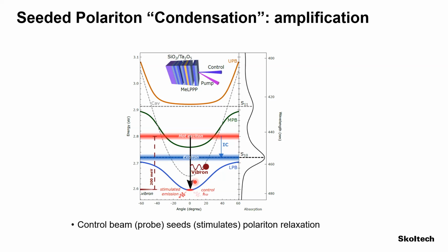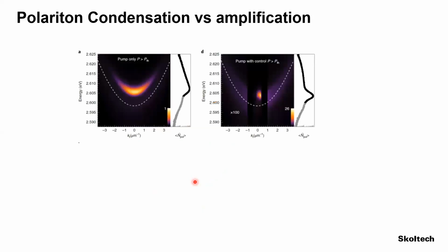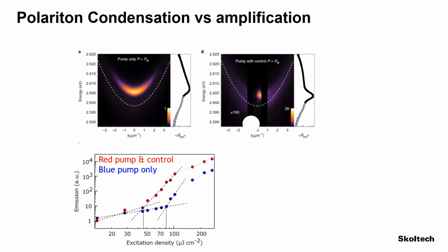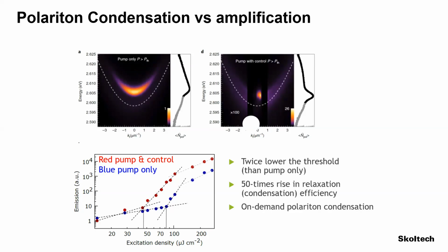So if I look at the dispersion of the system without the seed, I get a very nice distribution of energies. And if I look at the spectra here, this is a study that we did previous to this one, we see that we have very nice thermalization of the carriers, etc. When I seed the relaxation at the ground polariton state and I have amplification, I see that I amplify exactly the range of wave vectors that I have injected inside the system and at the energy where I am injecting them. And now if I compare the threshold, I see that I have a much lower threshold in the presence of the control beam. I can have a 50 times rise in the relaxation efficiency. I can really get amplification or condensation, if you want colloquially, on demand.